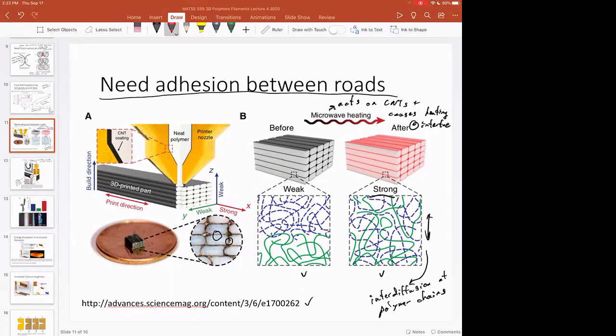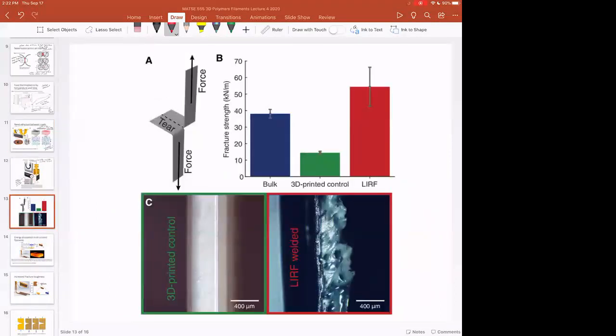Now, it might not be that we get perfect material properties from that, but you notice in this diagram here, where they're doing this process, they're getting material strengths that are on the order of the bulk strength of the part. So the error bars overlap here, so it's hard to exactly tell what's going on. And you have some nanotubes in there that might add to the strength as well. But this is looking pretty good because the bulk expectation is on the order of 40 kilonewtons per meter for the fracture toughness. 3D printing controls are usually bad. So here you're going to have poor interfaces.